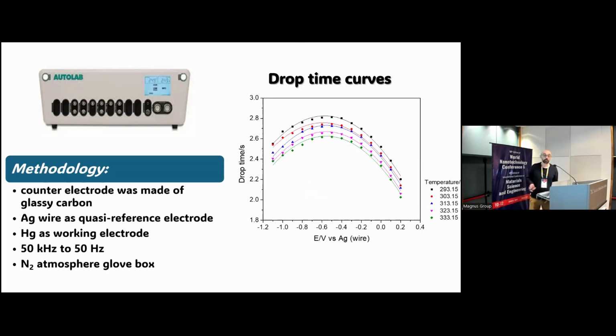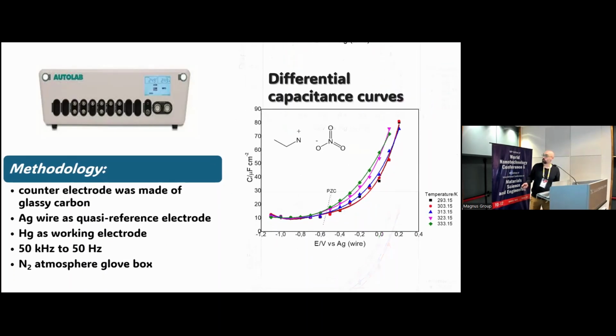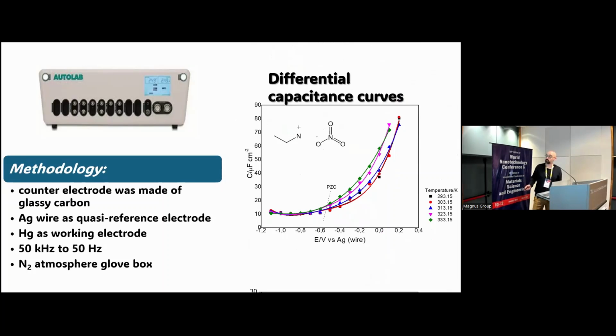And this is quite important in electric double layer compounds. You can see here the differential capacitance curves and here the potential of zero charge that I was talking about. You can see that there is quite an asymmetric U-shape. This U-shape is the reflection of the asymmetry in our compound, because ethylammonium is quite a bit bigger than nitrate, and this difference is reflected in the curve.